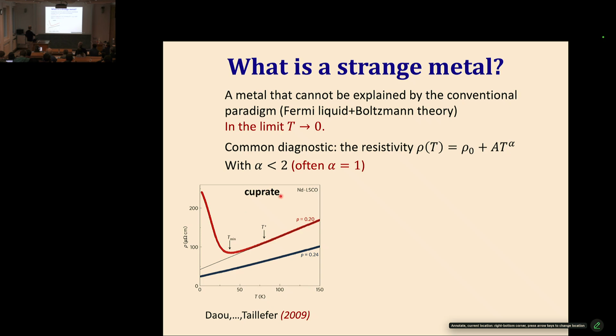This is a cuprate superconductor at various degrees of doping. Especially at this value of the doping, you see this beautiful linear in temperature resistivity that extends strikingly down to the lowest temperatures that you can measure. This experiment was done in the presence of a high magnetic field that suppresses superconductivity. Without the field, the sample would actually be superconducting. But you suppress the superconductivity by a field, and this linear dependence of the resistivity extends down to the lowest temperature that people have measured, below 1 Kelvin.